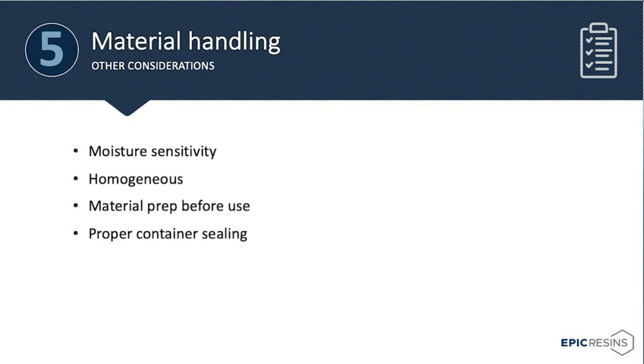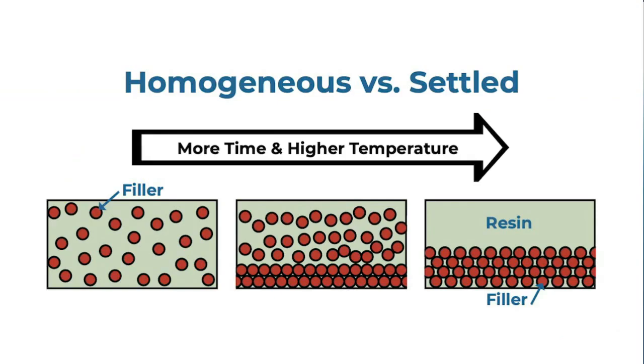Homogeneous material is important. All materials that contain functional fillers will tend to settle to the bottom of the container. This is the same reason why it is recommended that paint be stirred before use. In this slide, we talk about a homogeneous material versus a settled material. On the far left, you see the filler evenly dispersed throughout the polymer. The center slide shows partial settling of those solid particles that will slowly fall to the bottom of the container. And on the far right, you have an extreme example of settling where the filler is completely settled to the bottom and the resin is above that. This is an extreme example of filler settling and not typical for most products, but is an important property to understand when using a filled material.